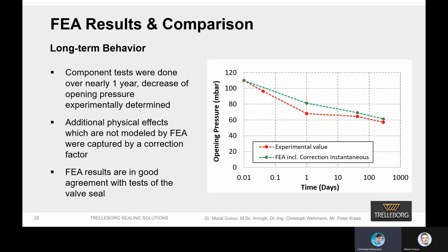And to verify our method, we did some tests on this component. Of course, here again, we cannot test for 20 years, but we tested approximately 1 year, so really a long test here of such a valve seal. And you see, we were able to quite nearly fit or predict the experimental values here.